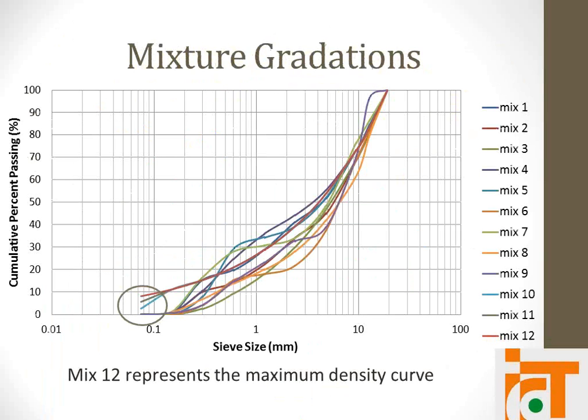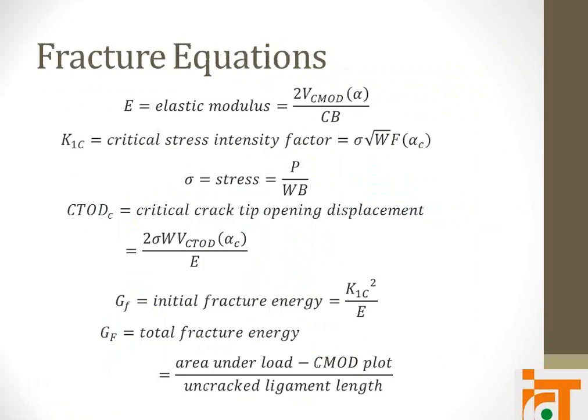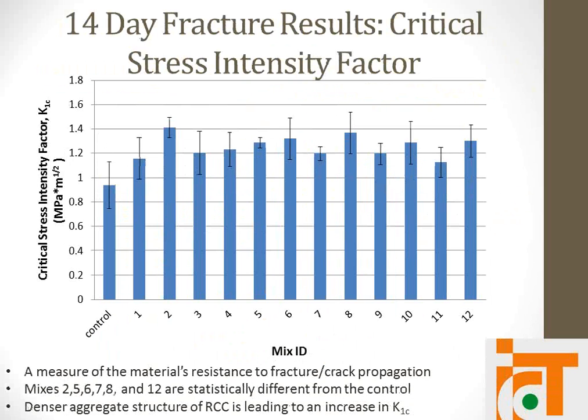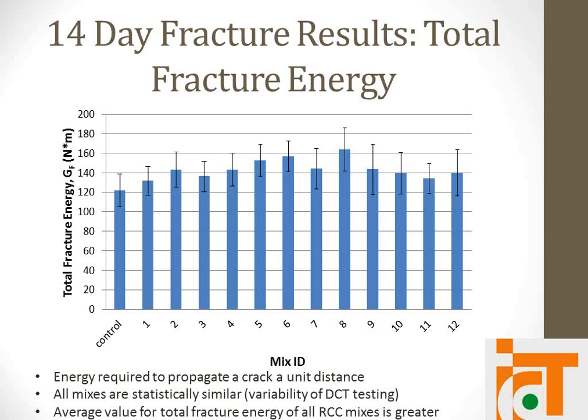Could you go back to the stress intensity plot? Okay, and then you didn't show fracture energy in this presentation, did you? Total fracture energy, yes. Okay. And you probably ran stats analysis on these results. Did you find that they were statistically different or significant? The COVs for total fracture energy are around 10, 12%. So we can't really statistically conclude that there's a difference between the control or typical Portland cement concrete and RCC, at least for total fracture energy. But from the average values, they're higher.